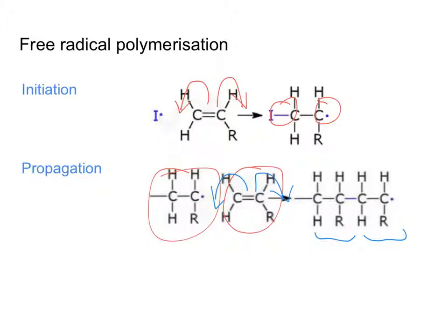and that will continue as more monomer units are available to the reaction. Now, one of the really fascinating things about polymerization reactions is they are very much like a recipe. Because there's this random element to these reactions, where they're reliant on the collision of monomers with these growing chains, it is very common for commercial production of these polymers to limit the amount of monomer and slowly add it to the reaction in a very controlled fashion. In the business, this is called starving the monomer concentration. Alright, and they do that to carefully control the reaction.